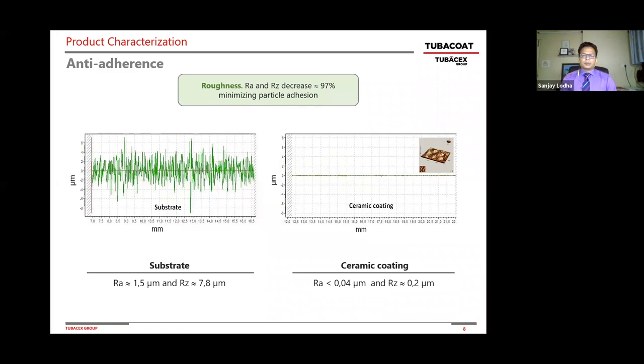Next slide, please. So this particular slide is very interesting, it shows the roughness of these coated tubes. What you see on the screen is, on my left, a substrate that's not coated. On my right, the same substrate that's coated. And if you look at the average roughness and the Rz, which is the highest point and the lowest point difference, you would see a drop of about 97% from the uncoated tube to a coated tube.